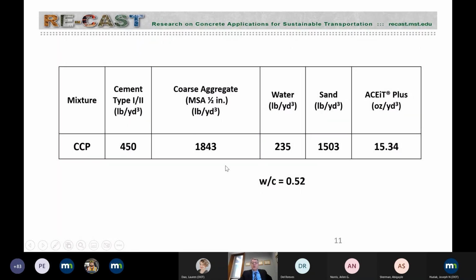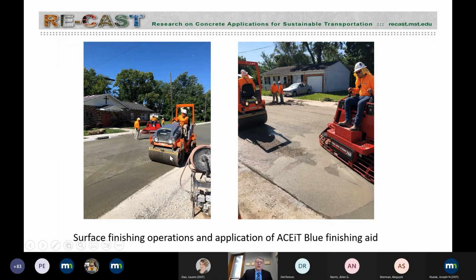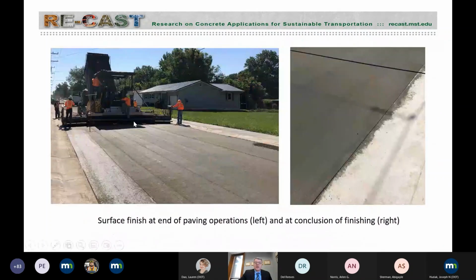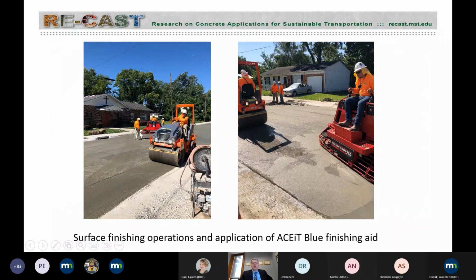0.52 water to binder ratio, 450 cements, and 1/2 inch maximum size aggregate. And here are a couple of photos of the finishing. Again, the concrete paver laid out the concrete. Yes, I have a slide of it over here. And then the finishing was done using very small rollers,